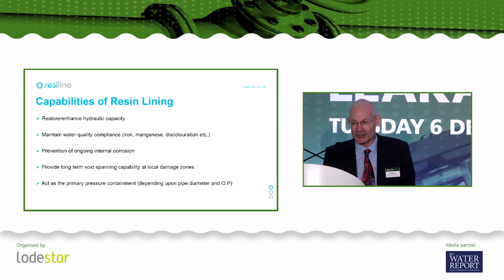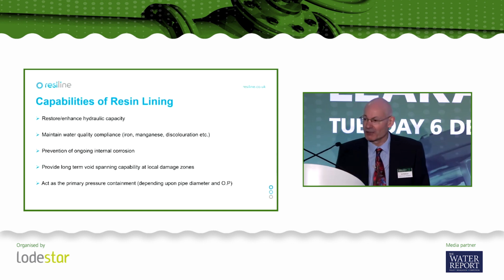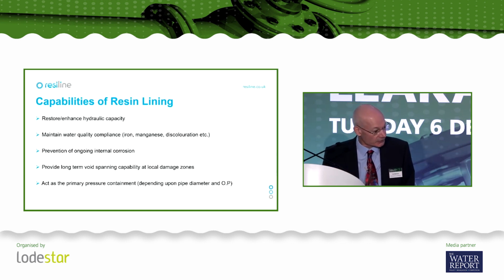Generally, that's things like discoloration or iron and manganese levels. It's generally assumed, and experience tends to bear this out, that once a main has been spray lined, that internal corrosion is effectively arrested. Obviously, you can't do anything about external corrosion, which can continue apace in some circumstances. So those aspects really apply to linings generally.